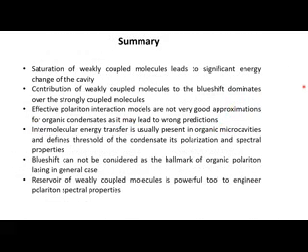Finally, I would like to stress that the contribution of weakly coupled molecules, so-called dark molecules, to the nonlinearity of organic condensates is very strong. In our particular case, it is even stronger than for bright molecules. Therefore, I would say that effective polariton interaction models are not very good approximations for organic condensates, as they may lead to wrong predictions. Also, blueshift cannot be considered generally as a hallmark of organic polariton lasing.